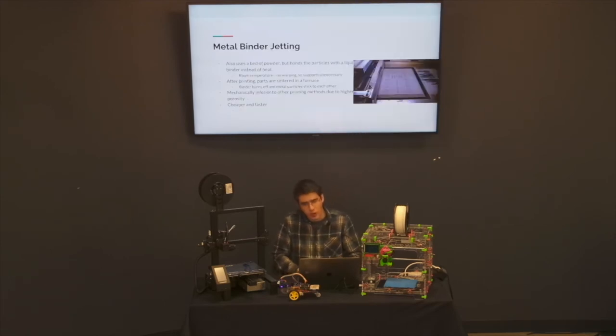Another option that you don't see quite as often is metal binder jetting. This one's actually significantly cheaper than the other, mainly because of how it works. Instead of actually heating and melting the metal powder with a laser or an electron beam, it uses basically an inkjet nozzle to jet in a liquid binder, basically a glue, to stick these pieces together. Once you've printed, you have a very fragile part that's basically metal powder that's been glued together. You put it in a furnace, the binder burns off, and the metal particles stick to each other. They sinter and the edges stick. Mechanically speaking, this is inferior to other printing methods. You get a lot of porosity from the gas produced by the binder burning off, and you don't get complete adhesion like you would with, for example, selective laser sintering.